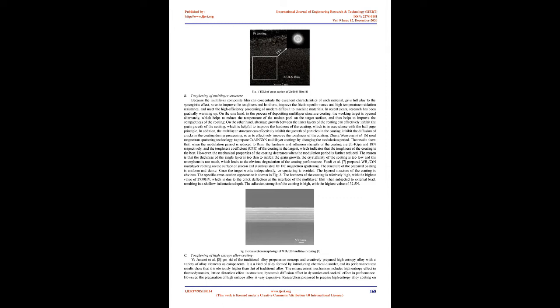The structure of the prepared coating is uniform and dense. Since the targets work independently, co-sputtering is avoided. The layered structure of the coating is obvious. The specific cross-section appearance is shown in Fig 2. The hardness of the coating is relatively high, with the highest value of 2930 HV, which is due to the crack deflection at the interface of the multilayer film when subjected to external load, resulting in a shallow indentation depth. The adhesion strength of the coating is high, with the highest value of 32.5 N. Fig 2: cross-section morphology of WB2/CrN multilayer coating [7].